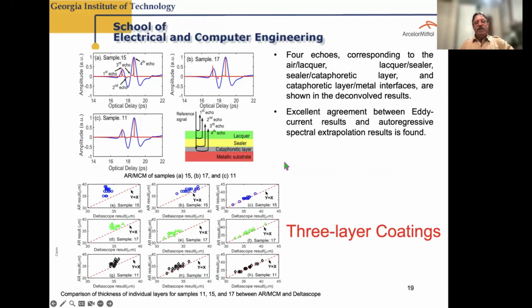So we can actually do this with a single measurement. So again, these blue curves are actually the experimental signals, but the red curves are after signal processing, obtaining the different reflections that are then used to determine the layer thicknesses. So I don't want to spend a lot of time here, but in fact, it works down to on the order of 10 microns for these materials.